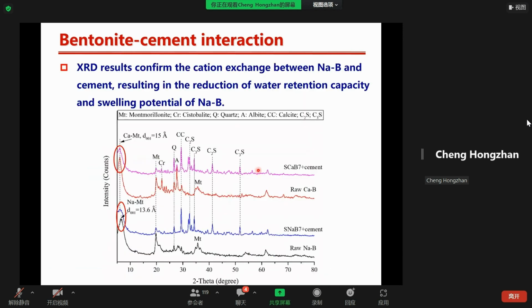For selected cement bentonite mixtures, we conducted the XRD test. The result confirmed the cation exchange between the bentonite and the cement, and this reaction led to a significant reduction in the water retention capacity and the swelling potential of sodium bentonite. And we can also find that this reaction works very quickly.